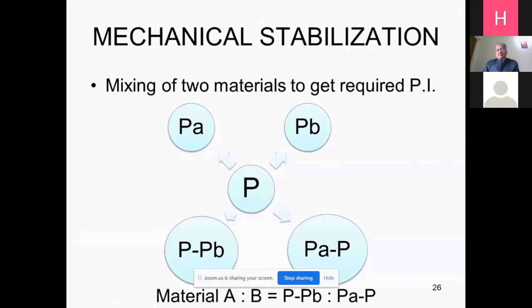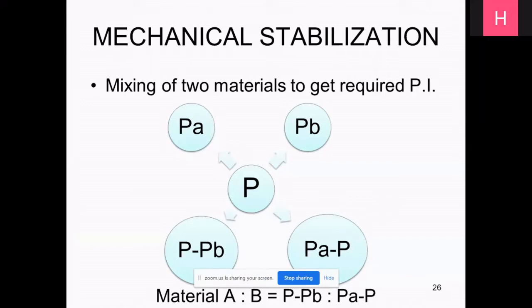Now, mechanical stabilization is there. If you want to use any material, normally a single material will not provide you the same gradation or the same properties needed by the recommended gradation or recommended property. So what you do is you mix 2 or more materials, and then find out the combination of these materials that fulfills the requirement of the recommended limits. The mixing may be done for 2 purposes, either due to grading or due to PI also. PI is the plasticity index, which is the difference of liquid limit and plastic limit.